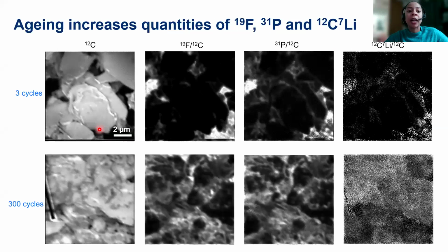So then we can directly compare how aging affects the intensities of the signals, and I chose to specifically look at 19F, 31P, and 12C7Li. On the top row, we have samples that have been cycled for 3 cycles, and on the bottom row we have 300 cycles, so this is a much longer aging time.